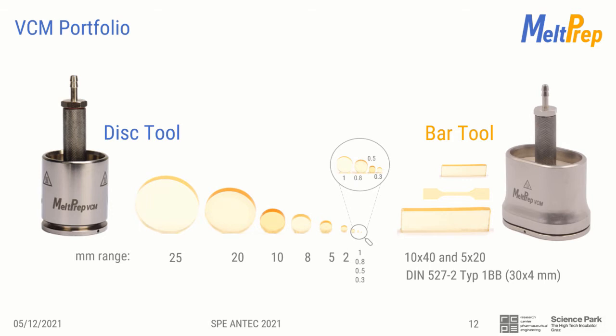You can make disc-shaped samples with a diameter between 25 mm and 0.3 millimeters, or you can do bars with the VCM bar tool, allowing you to have rectangular bars of 10 by 40 or 5 by 20 millimeter, or standard small scale tensile bars for the characterization of mechanical properties.